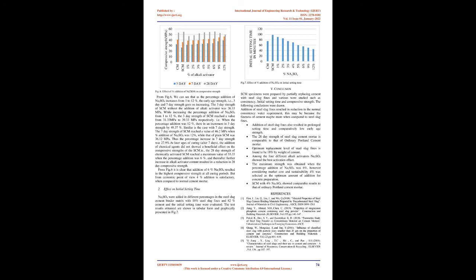This is because Na2SO4 is often used as the main component of concrete early strength agents, which plays an important role in improving the structure and performance of cement concrete. In addition, the compressive strength of samples with Na2SiO3 as an additional chemical activator after curing for 3 days reached a value of 30.33 MPa, Fig. 4.5. NaOH and Na2CO3 are less effective on improving the early age compressive strength of concrete.